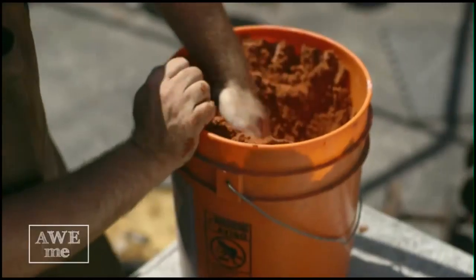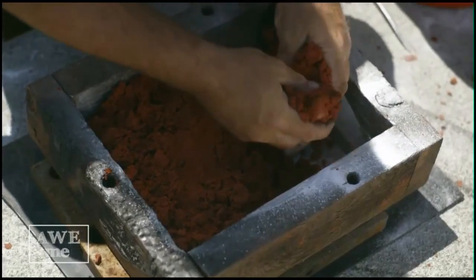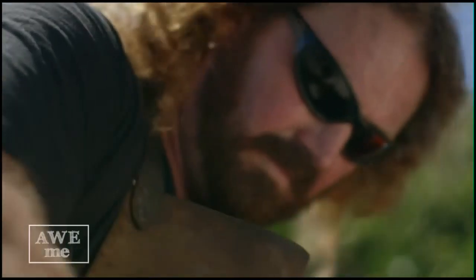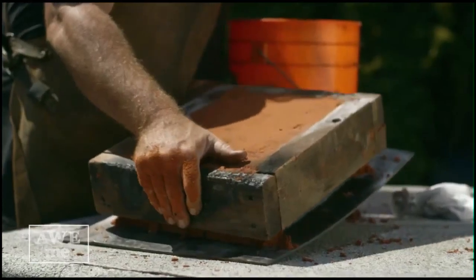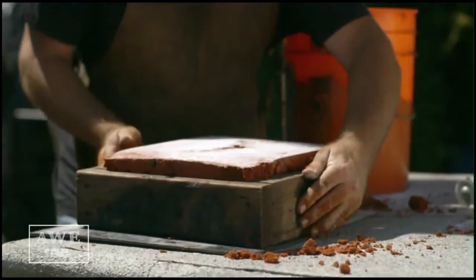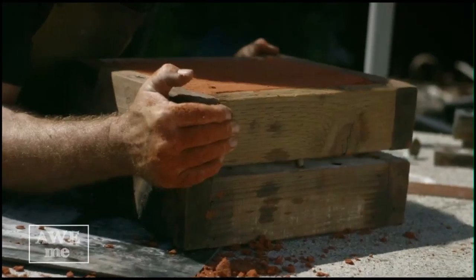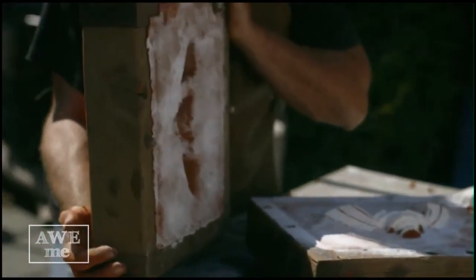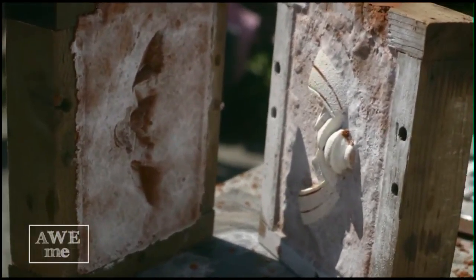In sand casting, as opposed to lost wax investment casting, what we're doing is we're making the cavity for the molten bronze to pour into by using a positive pattern that we make out of resin and press into the sand. The sand is a special kind of sand for foundry work for sand casting called Petrobond. Pretty much everything we do can kill you, but with sand casting, if you don't have everything totally dry, and you have one speck of water in there, it'll vaporize inside the piece and blow up. Once we have that shape inside the flask and we pour the molten bronze in there, it'll take on the shape of the plastic piece.